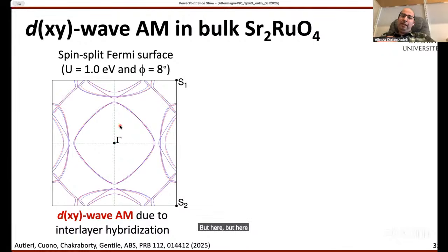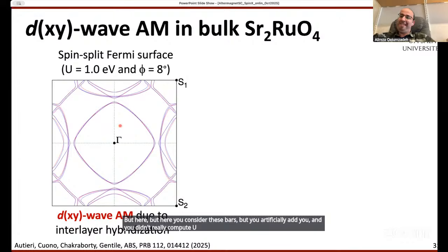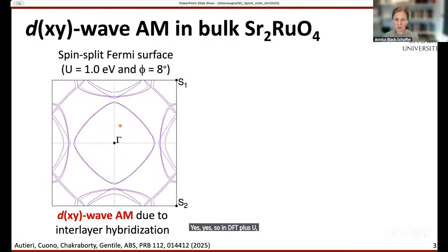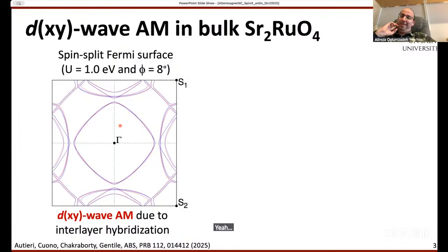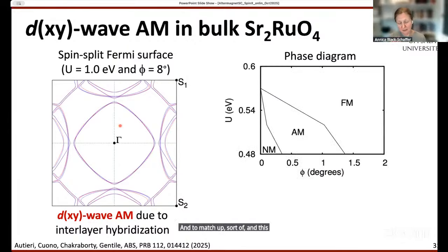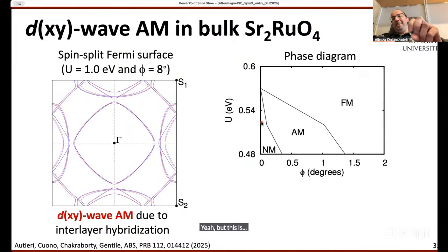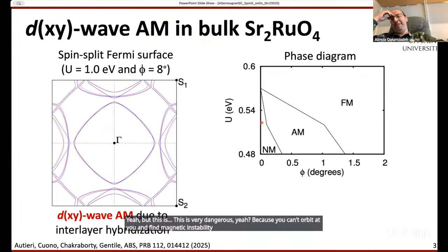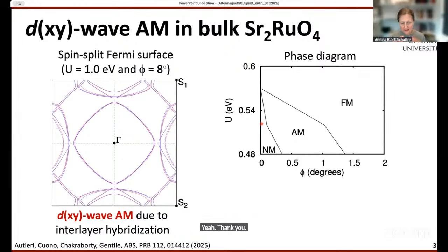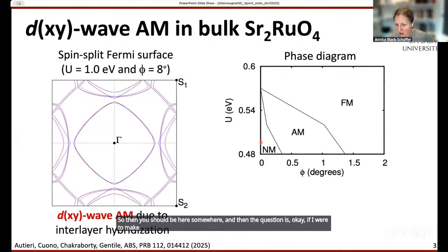But here you consider the bulk, but you artificially add U and you didn't really compute U, yeah? Yes. In DFT plus U, it is a parameter you put in. This is not my expertise, but my collaborator convinced me. This is very dangerous, because you can always add U and find a magnetic instability in every material. What I would say is that strontium ruthenium oxide is not magnetic, so U should be somewhere here. And then the question is, if I were to make a distortion, I can easily go from the non-magnetic to the altermagnet. So I would think I'm somewhere here in the real material.